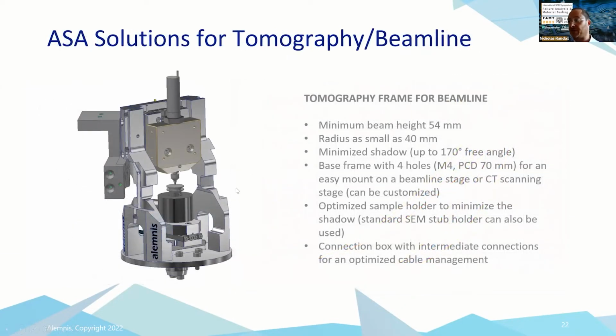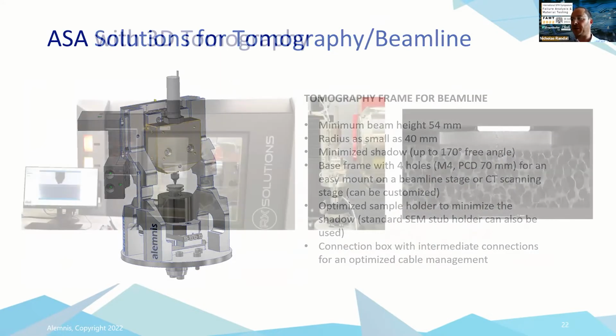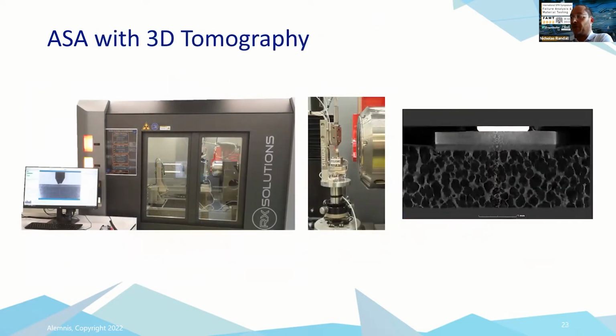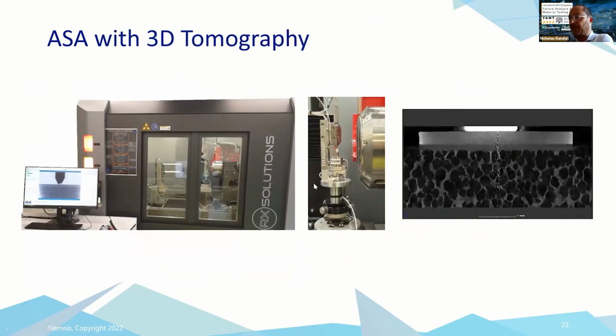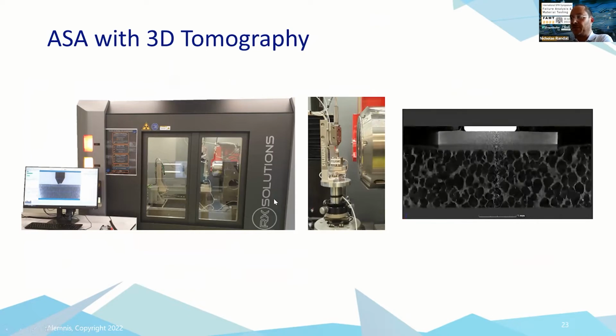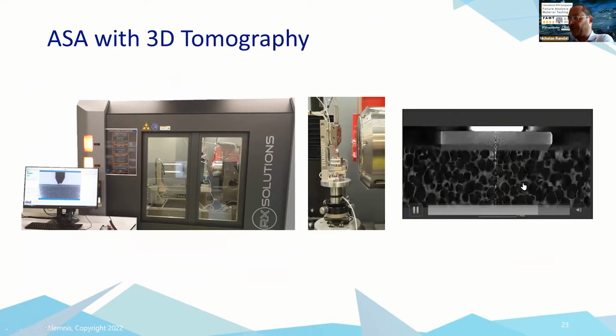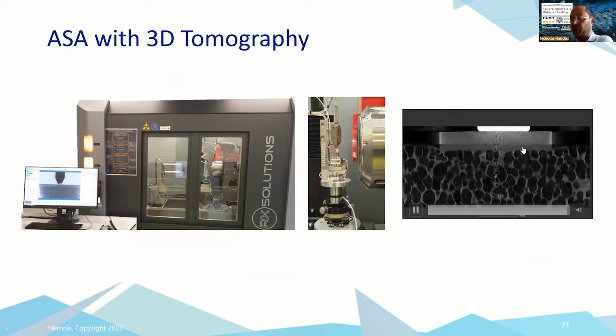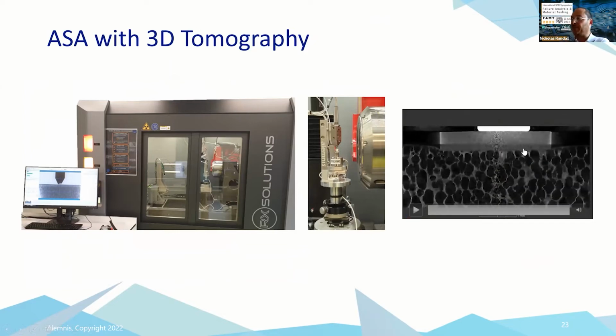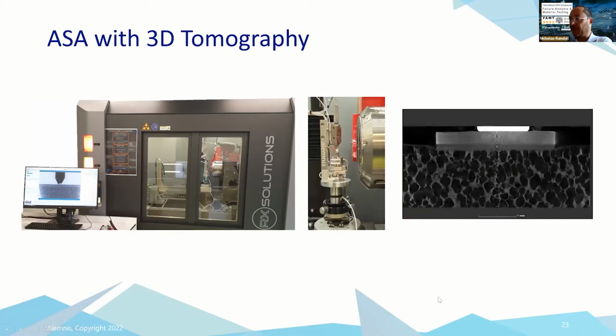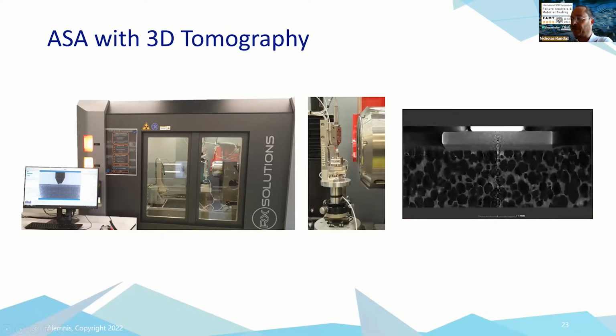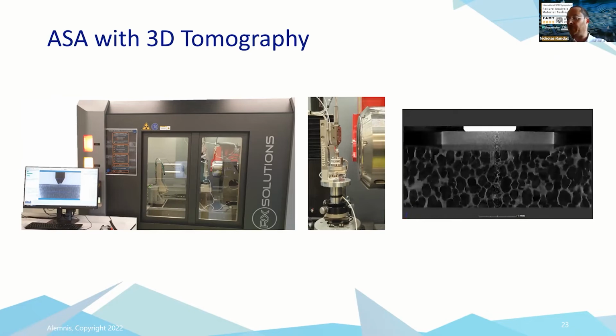We can also put the system in a modified frame for beamlines, so we can do tests in synchrotron beamlines or in tomography units. And we feel this is a way forward where we could test mechanical properties and measure the 3D tomographic image. So this is a system placed in an RX Solutions CT scanner. This is a polymer foam. We're compressing it from above, and while we compress it, we're rotating and building the 360-degree image of that foam structure. And this could also be very interesting for looking at semicon packaging.